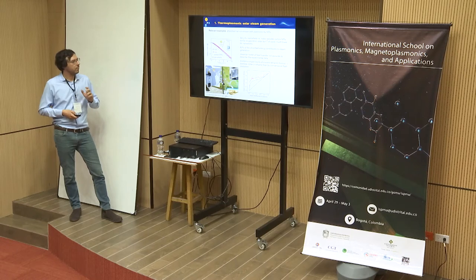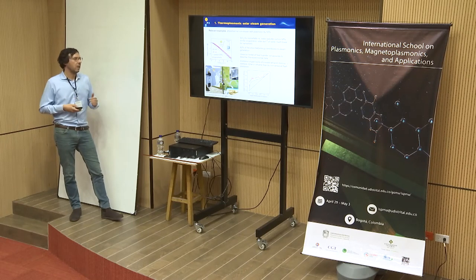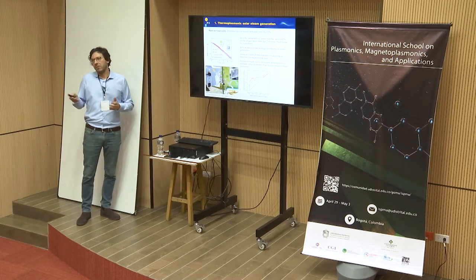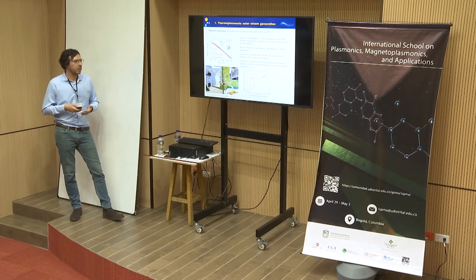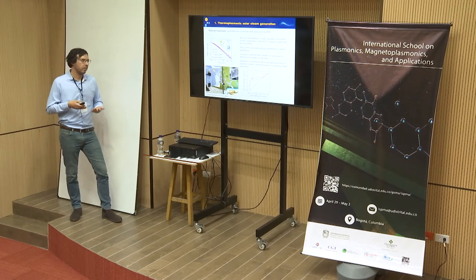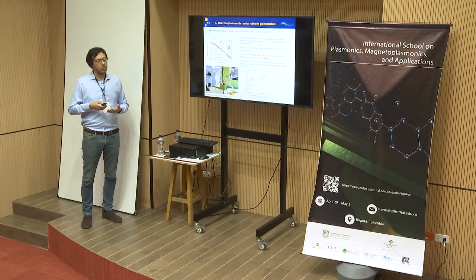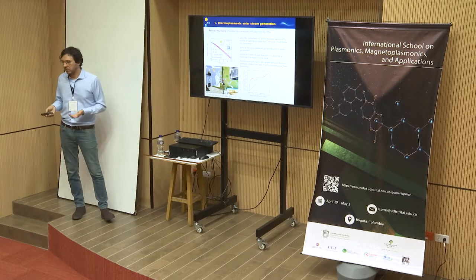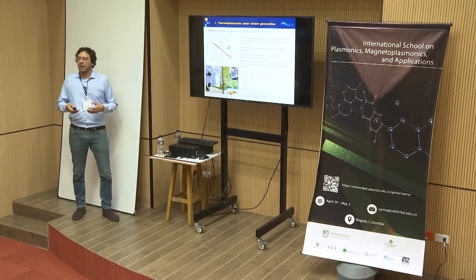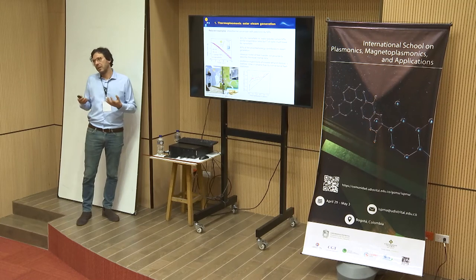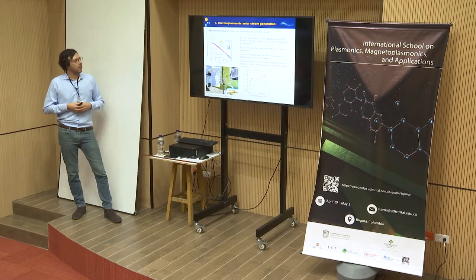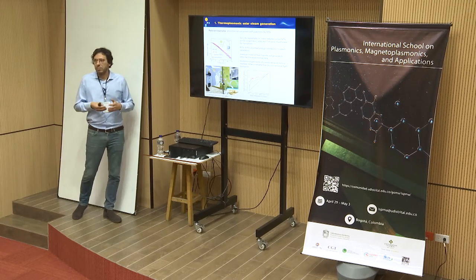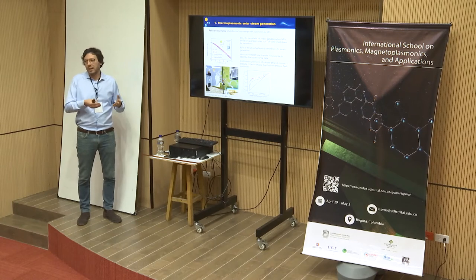In this example, they also demonstrate the possibility of using this evaporation to separate different chemicals. So, a mixture of chemicals like ethanol-water, methanol-water, as in normal distillation processes. And what they found was that the composition of the vapor was much richer in ethanol in comparison with thermal processes. So this probably tells us that the heating at the surface of the particles creates some really peculiar conditions to drive out-of-equilibrium processes, and so create different evaporation or distillation processes or equilibria which are not possible to generate in normal thermal conditions.